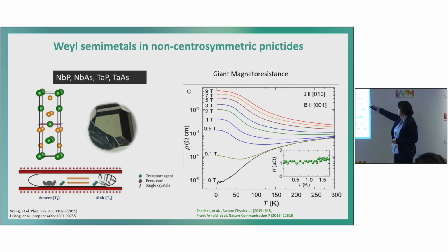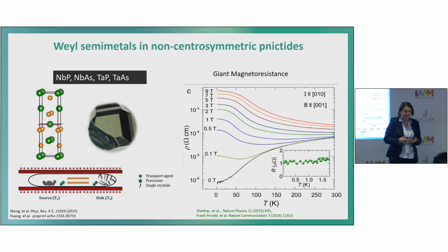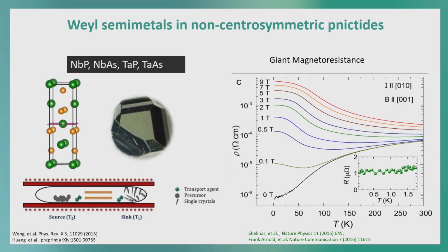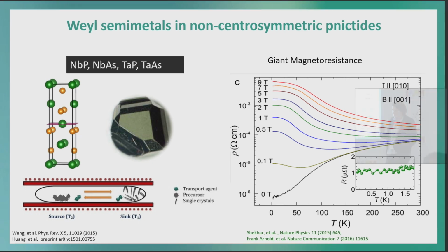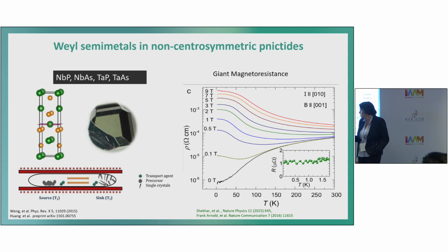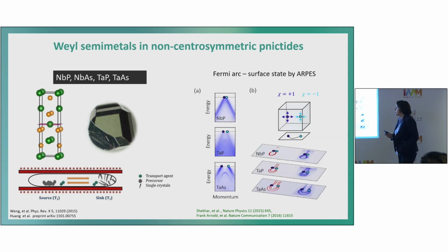But we like this compound especially because it still shows a big response at room temperature, and as chemists we always look for something which shows big responses at room temperature. For example, in magnetic Weyls we can use this for the Nernst effect, and we already see giant effects in the Nernst effect. This is all based on the topological properties, so we go far beyond what was expected by conventional theory in these materials.